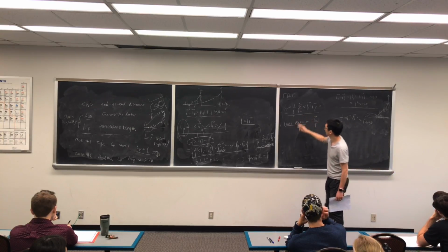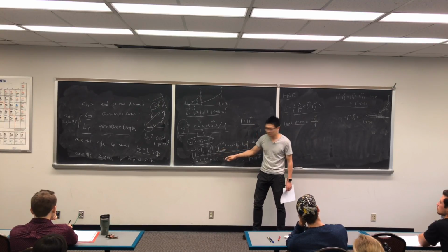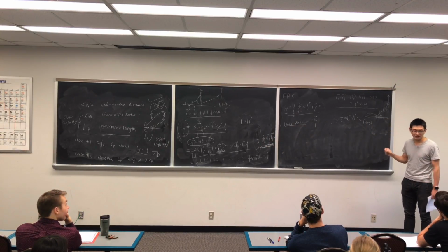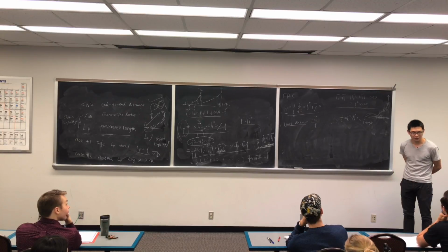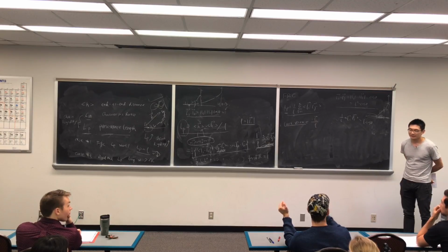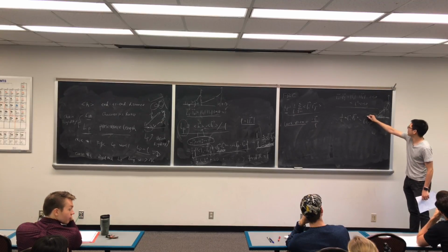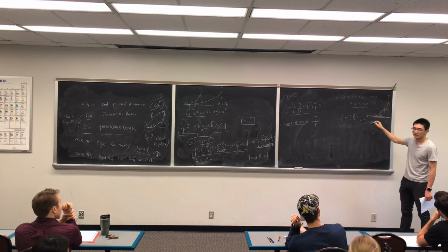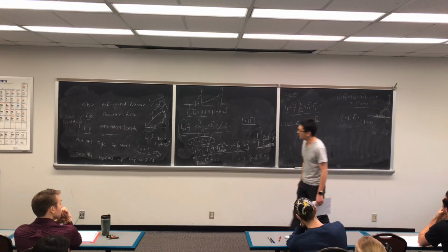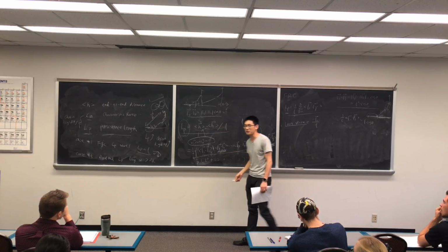So this term, the other way we write it is as an expanded term. Basically, the first term, second term, third term are these little by little distance projections along the first vector. So LP is the distance in x, not the length of the chain. It's basically the distance along the first bond. When does the chain start to bend over 90 degrees? That's why we started to talk about all these. I'm trying to explain the physical meaning first before we jump into the equation.